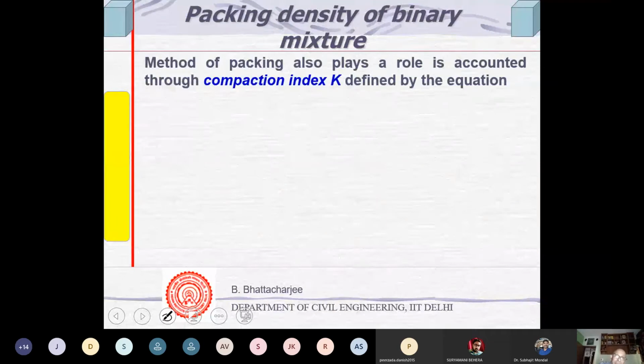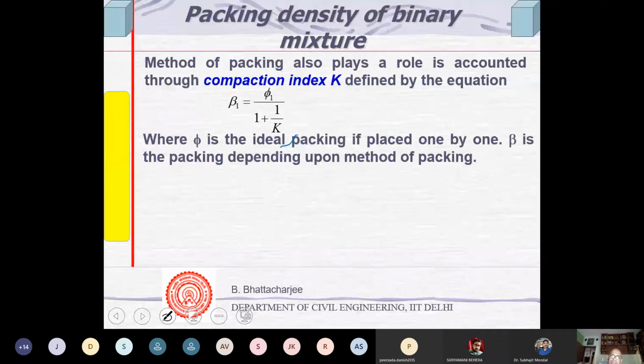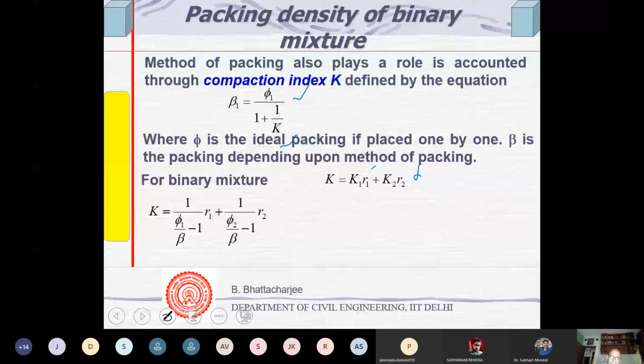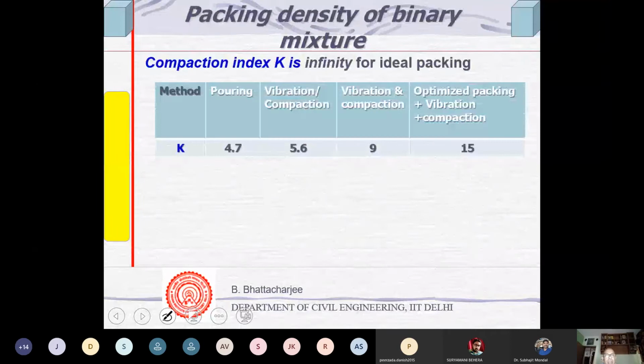and binary mixtures. Okay, the compaction method also affects it. And there's a compaction index. Packing will depend upon compaction. Phi is for ideal packing. And this depends upon the proportion of those materials, fine and coarse, for binary mixtures. K is given by beta plus, etc. There's some beta, I'll just define what this is. It's given by this formula. K is given by R1 by phi1, R2 by phi2, etc. And these coefficients are given. Compaction for pouring, 4.7. For optimized vibration, this is 15.